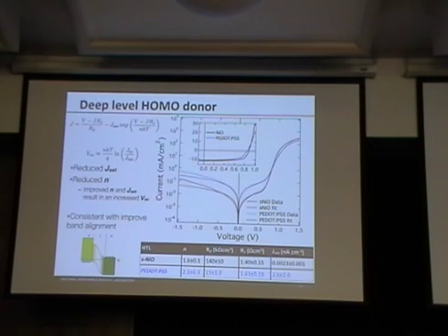But then the next question really is, I've done the solution-processed nickel oxide. I told you that I see no evidence for structure. When we have an amorphous system, what do we tend to have? I mean, we draw this nice band gap that's nice and clean. But if I allow for there to be disorder, what does that imply, typically? Trapped states, states in the gap, right? One could actually wonder, if it's an amorphous oxide, do I actually have a well-formed gap?